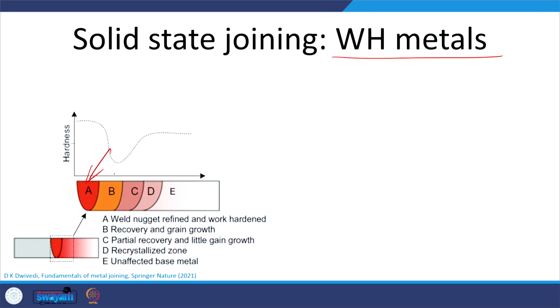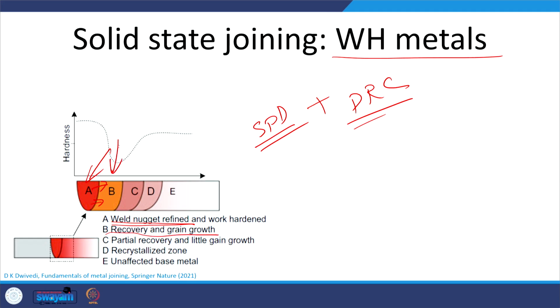then zone A will be subjected to complete refinement of the grain because of the severe plastic deformation that will be experienced, coupled with the heat generation that can also cause the formation of new grains. So, dynamic recrystallization occurs in the weld nugget area, and even in the ferrous metals phase transformation hardening can also occur in this area. But the zone which is next to the weld nugget area will be experiencing recovery and grain growth, and therefore we will be getting the softening of the HAZ in the work